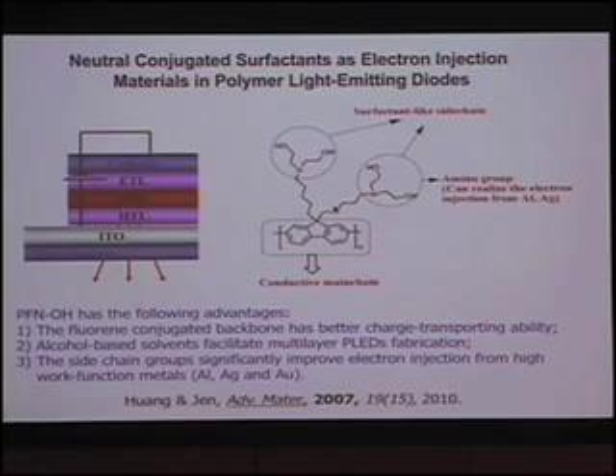But recently, we have tried to work on the electron transporting layer part. We have developed this so-called conjugated surfactant. This surfactant we developed can be generally soluble in alcohol as a solvent. This side chain serves a couple of different purposes. One is that the hydroxyl group will be chelating toward the metal electrode you evaporate on top of that, and the nitrogen here will form a positive surface dipole. As a result, you can adjust the work function of the top metal you use.